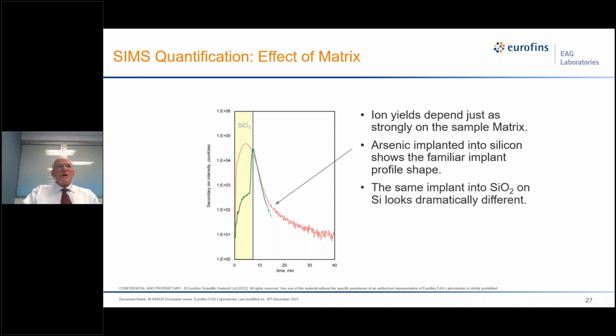It has the anticipated shape. If you grow an SiO2 layer on it and put the same implant through the SiO2, you get this totally ridiculous profile. And that's because the ion yield of arsenic is much, much less in the SiO2 than in the silicon. We have ways of calculating this, have standards of arsenic in SiO2, and we have some mathematical modeling ways so that we can meld together the sensitivity in oxide and sensitivity in silicon and get more or less a smooth curve. But the sensitivity difference here is so great that it's hard to completely remove the artifact. But SIMS is certainly subject to artifacts where the sensitivities of the elements are very different between the layers.